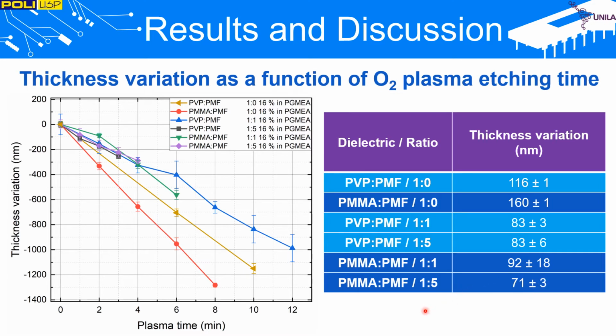Even though cross-linked films are harder to etch and consequently to open vias in integrated circuits, these results corroborate the presence of cross-linking already at 1:1 ratio.